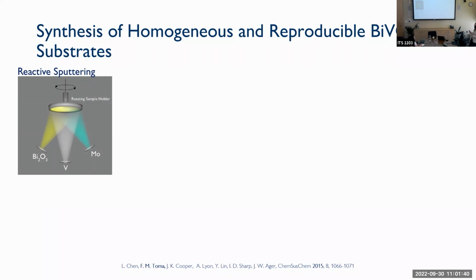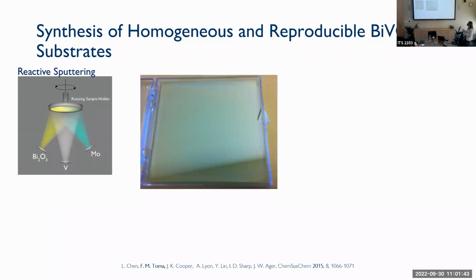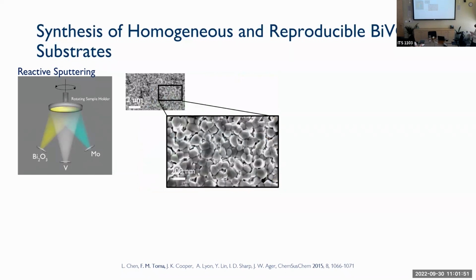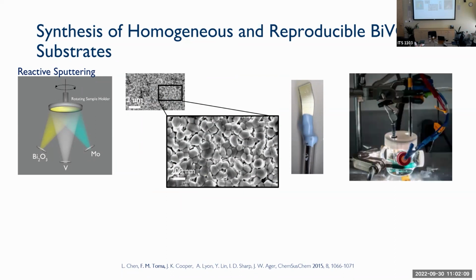This is the representation of a sputtering system. I made a 10 by 10 centimeter square slice of BVO just to show that the synthesis was reproducible on a large scale. This is how it appears at the nanoscale by scanning electron microscopy. So it's a polycrystalline granular material. You make electrodes. This is a lab-scale type of electrode that I will make. It's 1 centimeter by 0.5 centimeter, roughly. And this is the photoelectrochemical cell that I usually use to test materials. So as you see, the simulated sunlight is coming this way. This is the electrode that you see here.